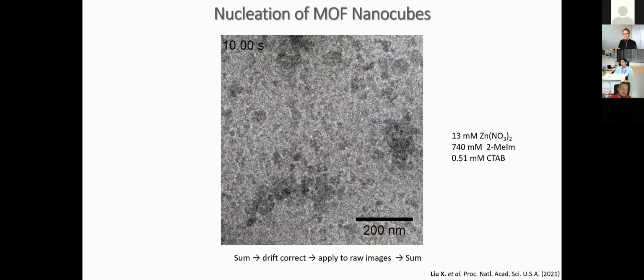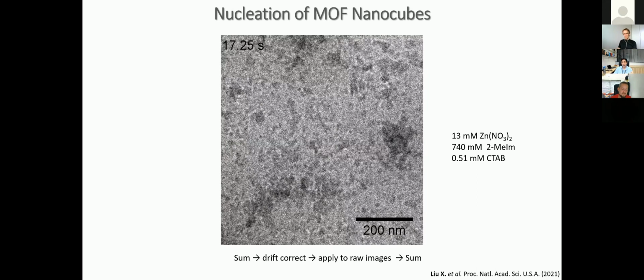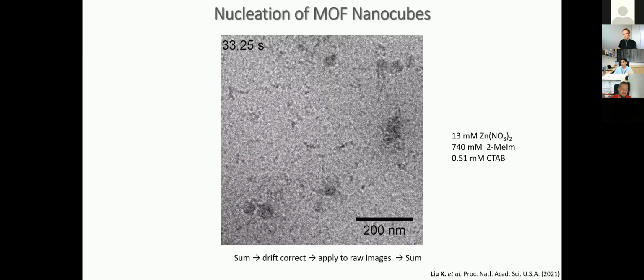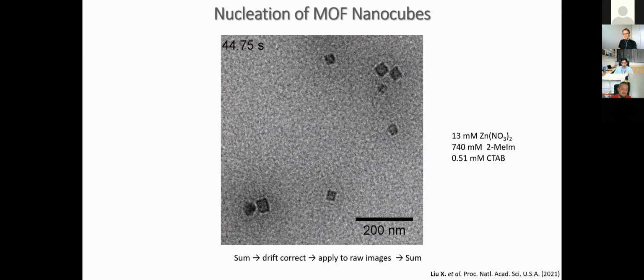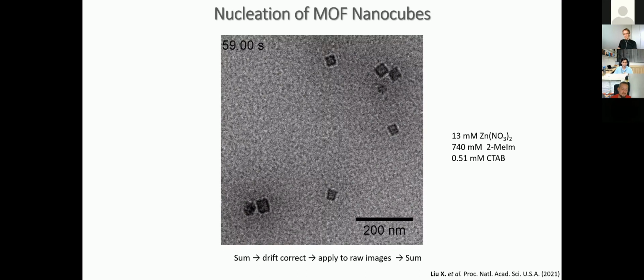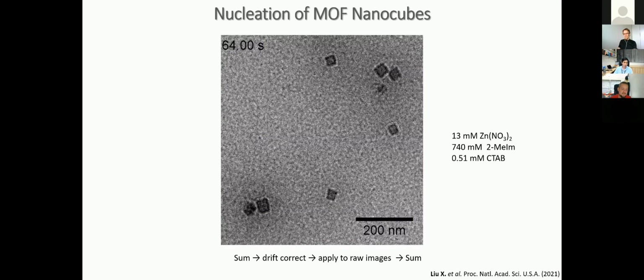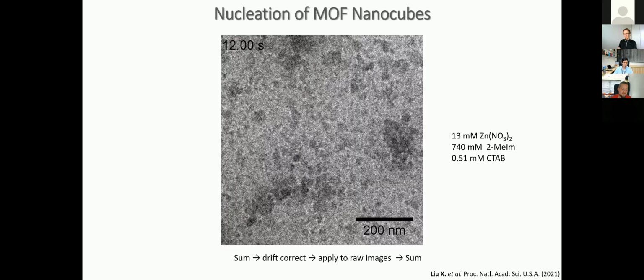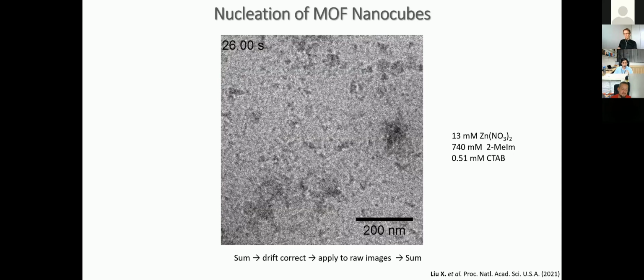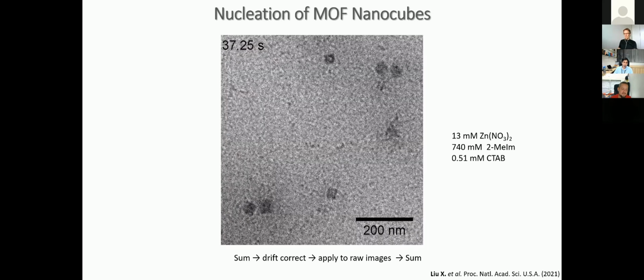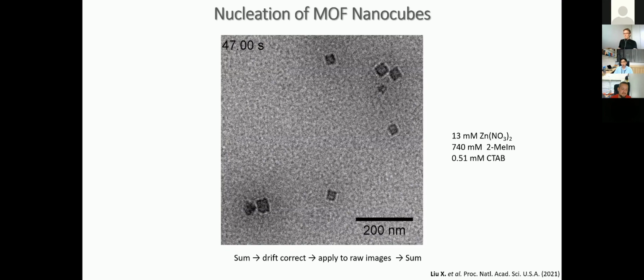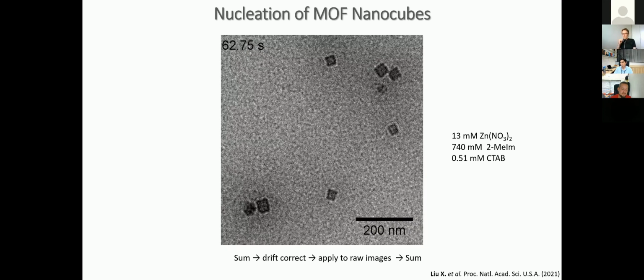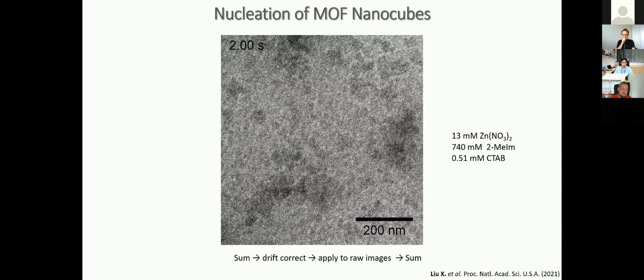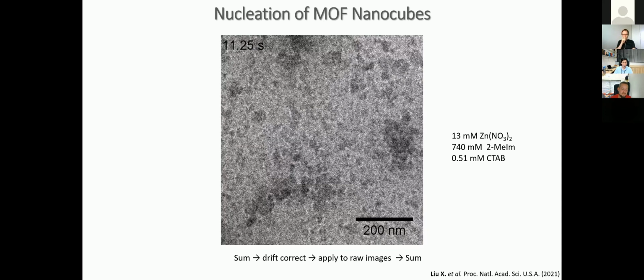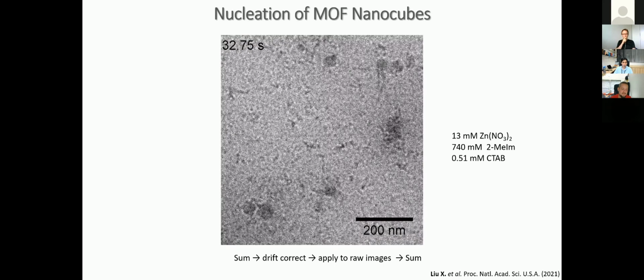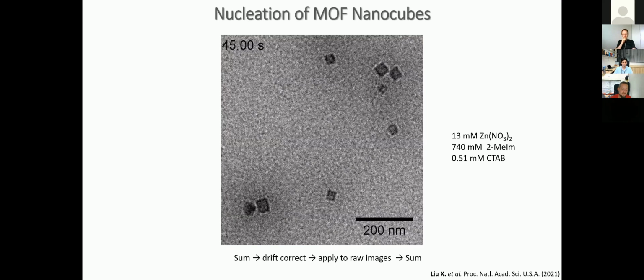So what we saw with the beam-driven phenomena for the gold nanoparticles, right? Gold, you can bombard it with electrons, it doesn't get damaged. Here you have a lot of organics, so these are beam sensitive. But you see the same process. So you can actually visualize the nucleation of the MOFs at extremely low doses. Well, yeah, you say this is low dose. How do I know this is a low dose, right? So you have to do more checks, because that's a key challenge of in situ TEM, right? How do we know that what we're seeing is still not affected by the beam?